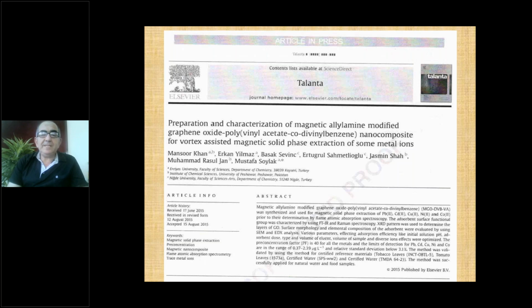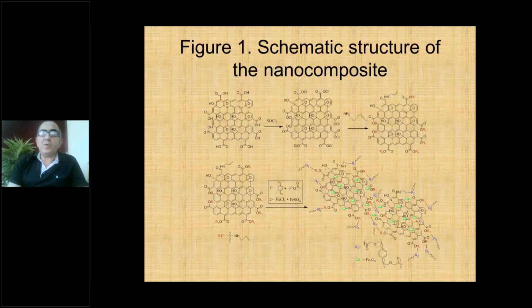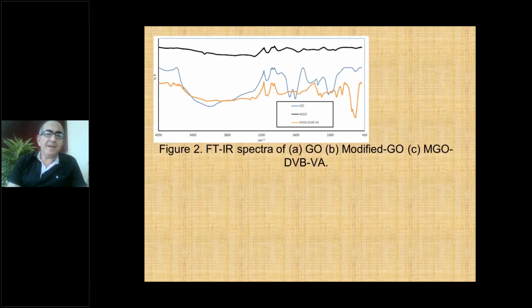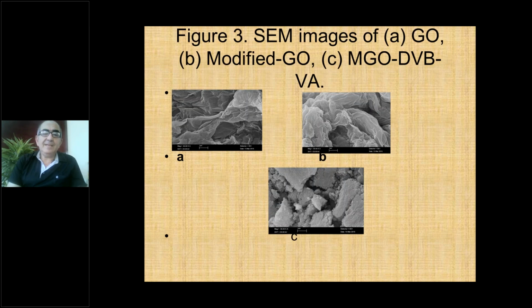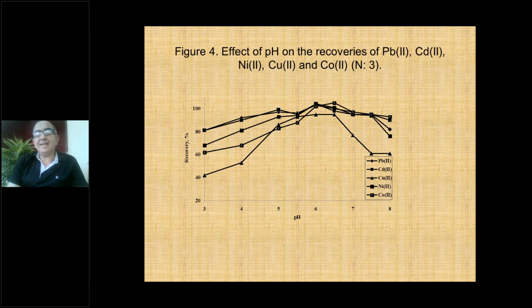Also, with all optimization steps, this is the schematic structure of the nanocomposites. I am not studying polymer chemistry. This study involved people working on polymer chemistry. They synthesized these materials, we characterized them, then we used them for solid phase extraction studies. All stages of the synthesis process were done by our colleagues. Then after characterization by using infrared and the scanning electron microscope, we used these materials for magnetic solid phase extraction studies of these metal ions.